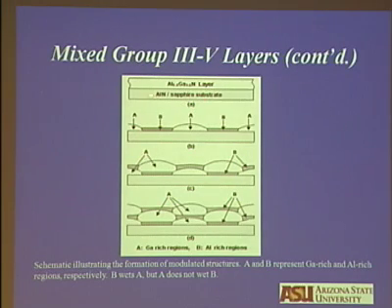You start growing aluminum gallium nitride on aluminum nitride on sapphire. This is a sapphire substrate. This is the buffer layer you grow on it. And we showed that these layers phase separate. The aluminum-rich regions wet the underlying aluminum nitride, but the gallium-rich regions don't wet. And that's what is illustrated. Their structure is shown here. You now deposit on these. There is asymmetry in wetting behavior.